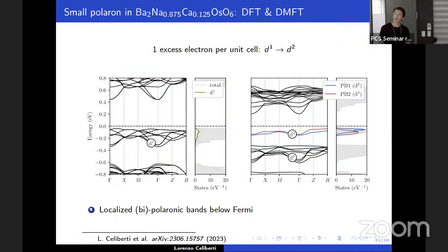If you look at the band structure compared to the pristine case, you have on the left the band structure of the material without doping. The dashed line is the Fermi energy. You see this bunch of bands corresponding to the osmium d electrons, the occupied ones, whereas you have the d unoccupied states above. When you do the doping, you have the formation of these two states corresponding to the polaron. Calculating the charge density of these two bands gives you the shapes I showed you before.